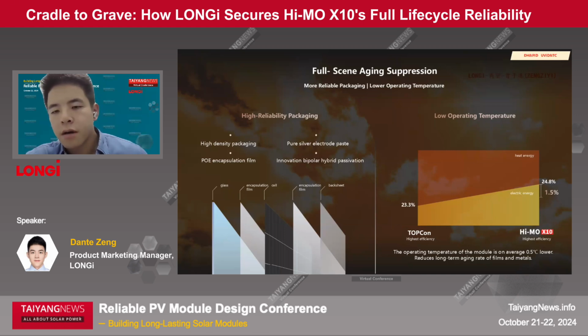But for our Hi-MO X10, because we have higher efficiency, we can absorb more sunlight energy and turn it into electrical energy, and we reduce the heat that way. And the temperature, we just say that 0.5 is not that high, right? But this 0.5 will lead to slower aging of the overall materials, like the film, the frame, the glass, the ribbon. They're all affected by temperature. If we can drop the temperature down, we can extend their lifetime and reduce the degradation, by the way. It's a very important part, actually.